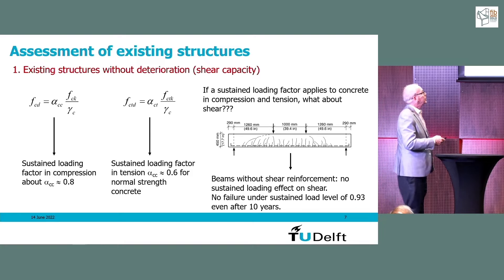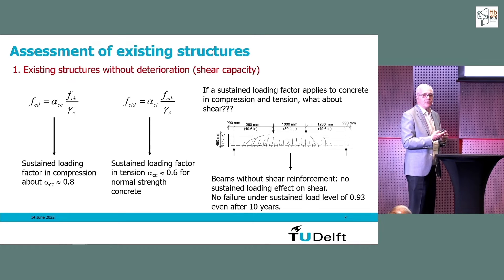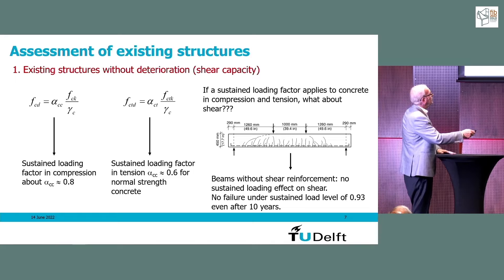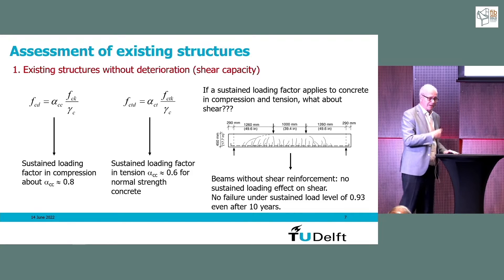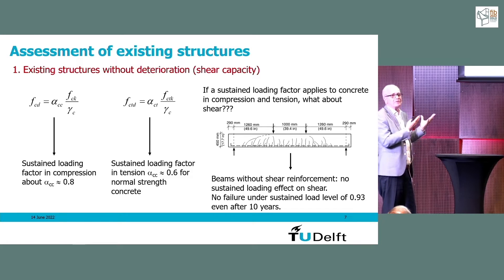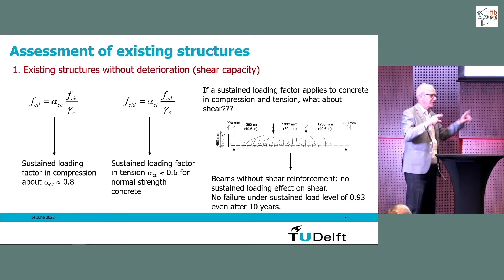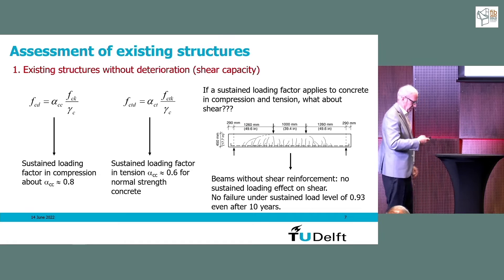The reason is that aggregate interlock plays a very big role in shear capacity. If any sustained loading effect causes a shear-tension crack to grow slightly, the aggregate interlock compensates — it is a hardening effect. Therefore we could use the higher concrete tensile strength with confidence. But all of this requires understanding: not just knowing where to drill and what the coefficient of variation is, but also sometimes needing tests to understand the behavior.